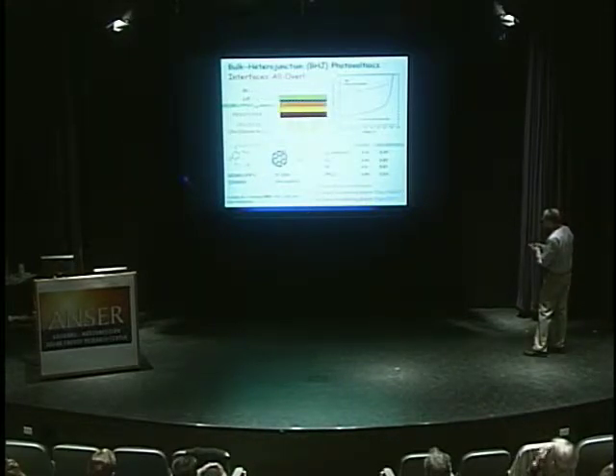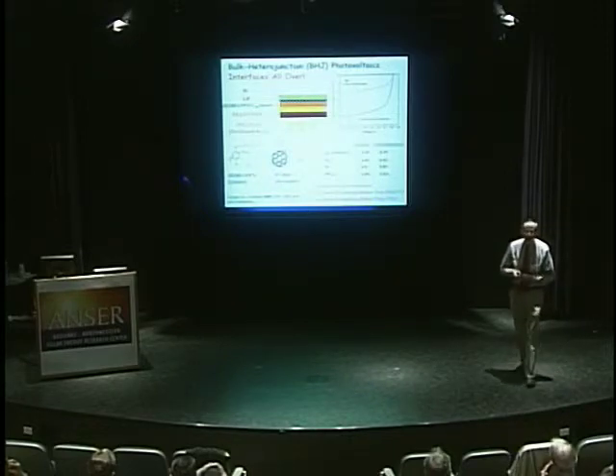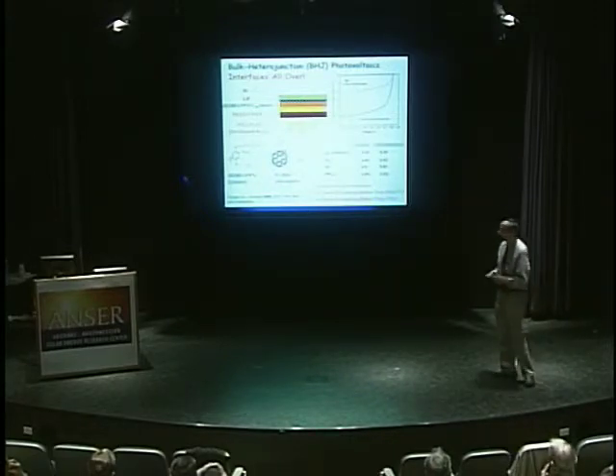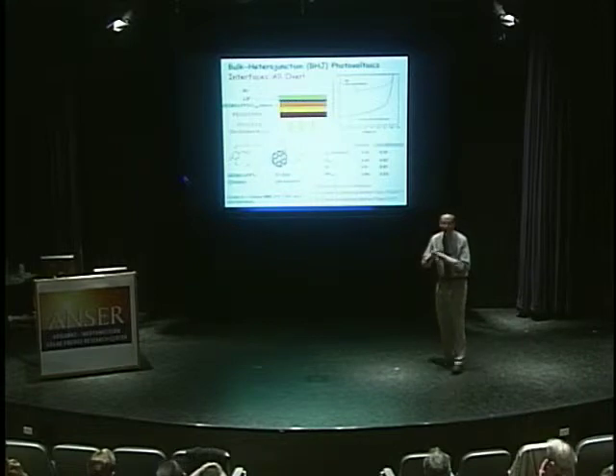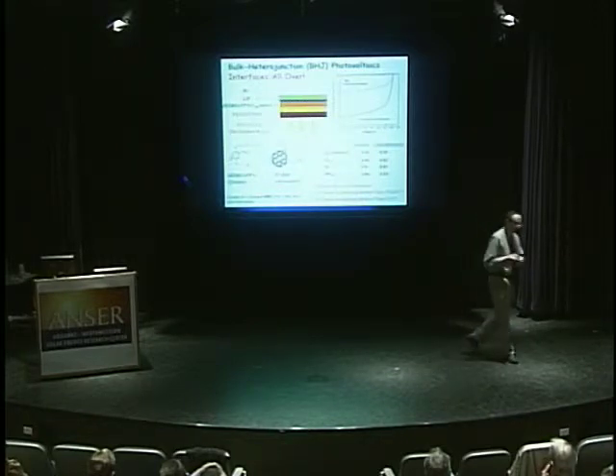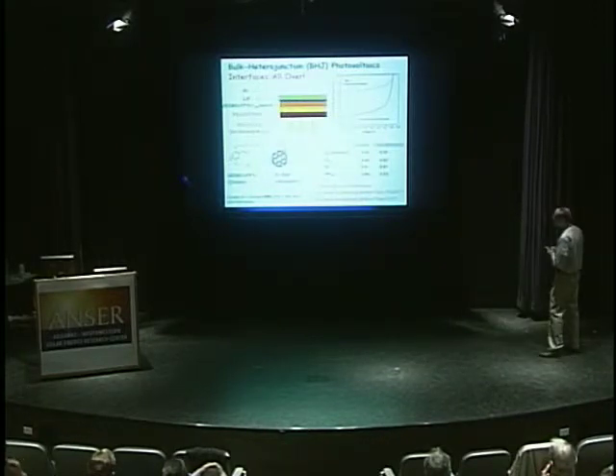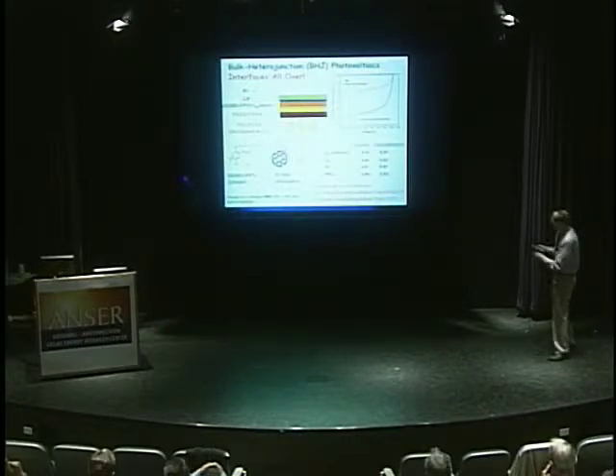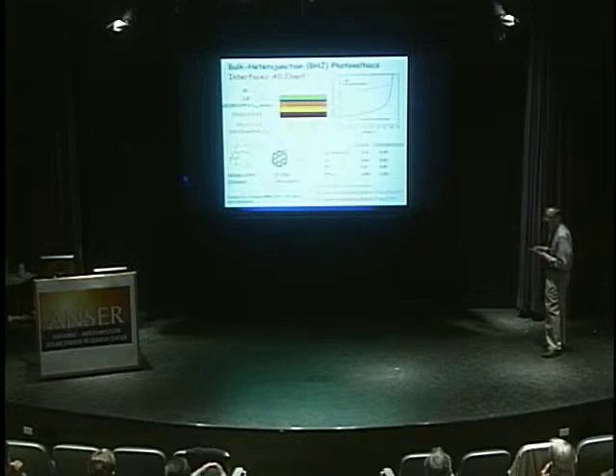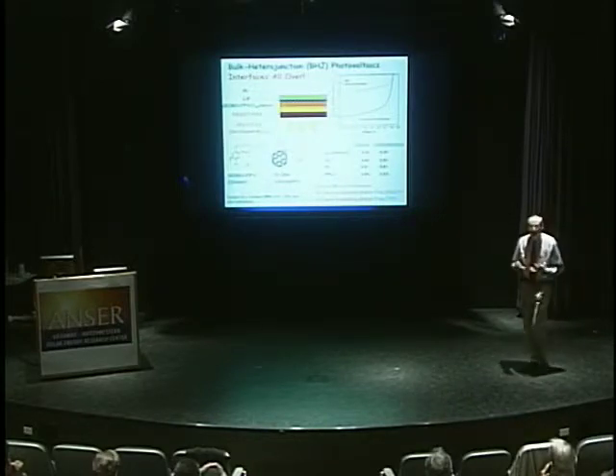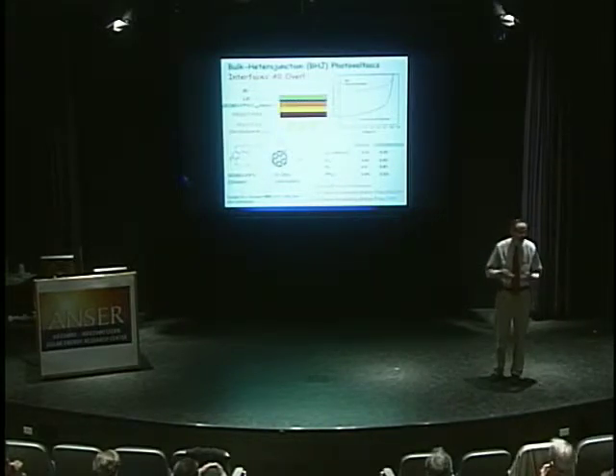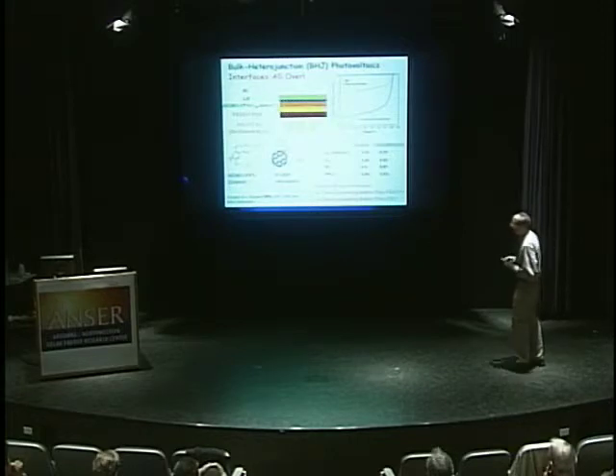So here's the anode, indium tin oxide. Indium tin oxide is awful stuff. It corrodes. Indium is scarce. It's not an earth-abundant material. It certainly doesn't have the conductivity we need. And then on top of it, the interlayer that's usually used is something called PEDOT, which is a conducting doped polythiophene. It's got a pH of about 1. It will corrode the ITO.